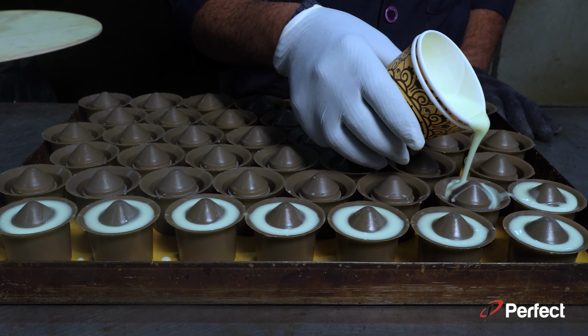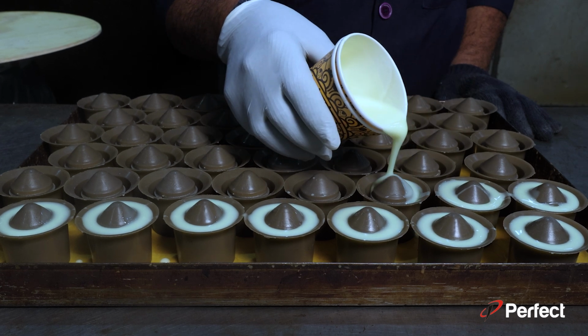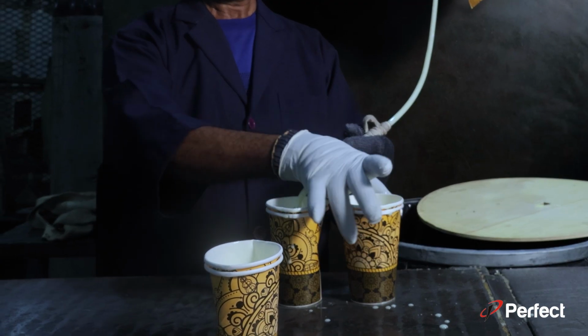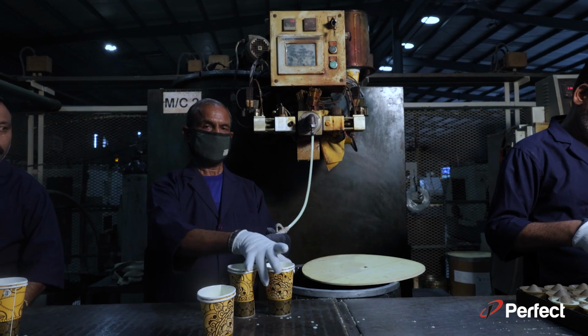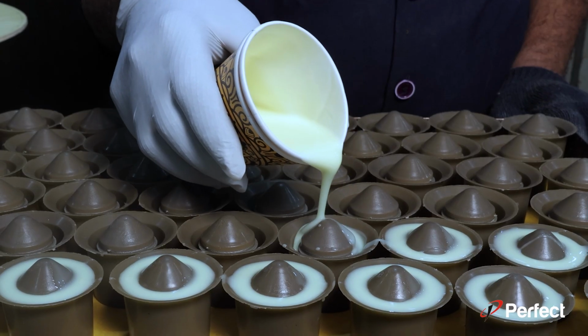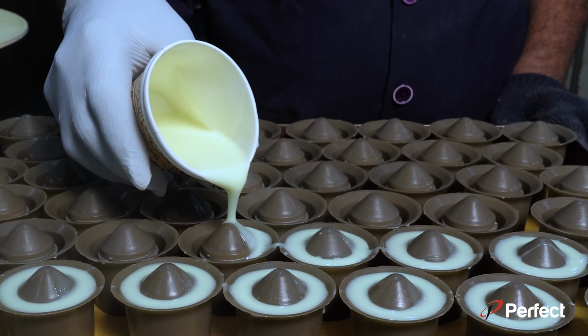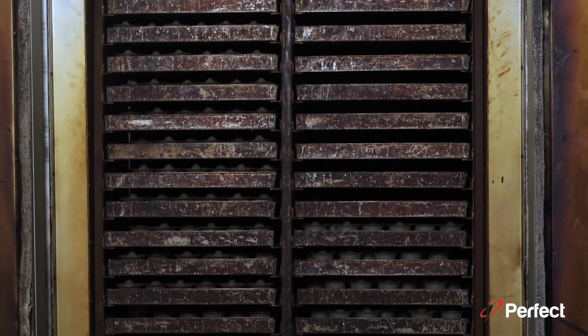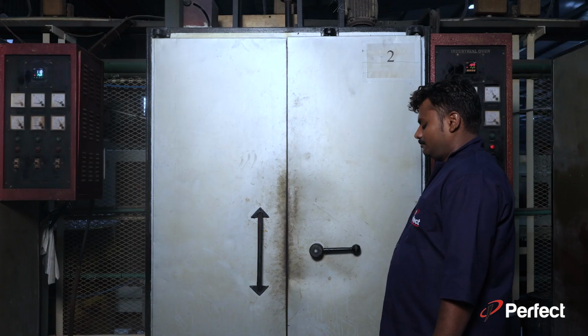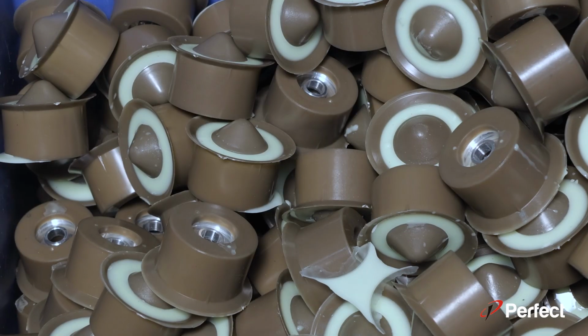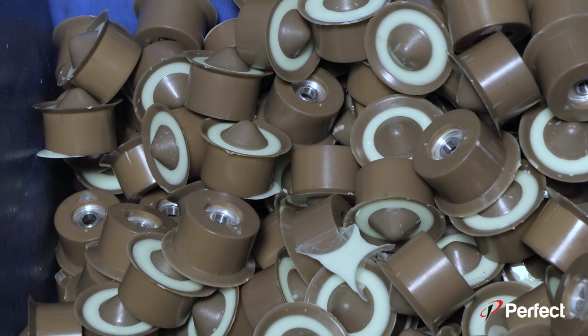These heated inserts and cups are then arranged in trays and filled with PU material using a 2-component PU casting machine from Bollé, France. The trays containing PU-filled inserts, enclosed in the cup molds, are again placed in an oven and heated at 80 degrees Celsius for 20 hours to achieve requisite quality and hardness.